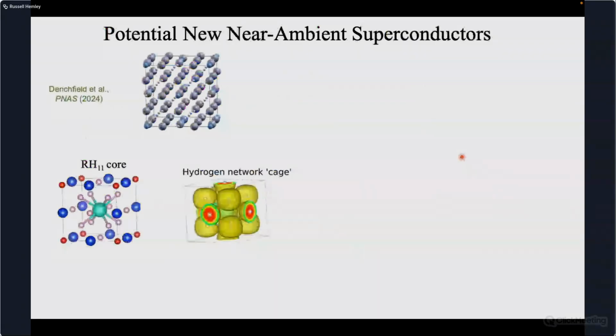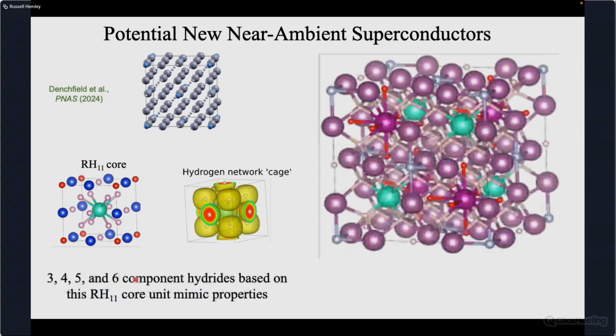Well, my student took this further and asked the question, well, can we replace lutetium with other elements, maybe combinations of elements, to realize the same kind of phenomena at low pressure? And this is, again, a theoretical calculation. And what he recognized is that this structure that is proposed has a kind of core unit, an RH11 core. But if you start replacing the atoms in this core with non-lutetium, you can build very interesting structures going from 3, 4, 5, and 6 component hydrides.